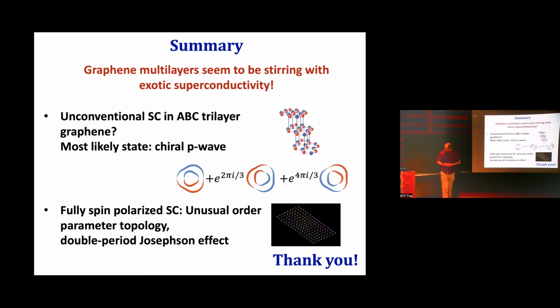Right. So none that were discovered so far, except in one regard. The reason why the cuprate superconductors got so much attention is, of course, because the Tc was so high. They lost their crown as the highest temperature superconductor, but at ambient pressure they're still by far the highest. So the promise is that unconventional superconductivity is a way to get to higher Tc. So basically you're pushing Tc higher.